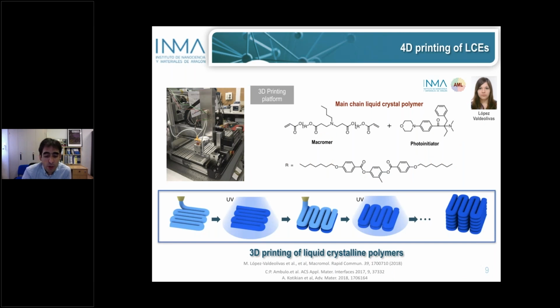In this scenario, we have developed a printing platform of liquid crystal elastomers. We did this at the same time and independently from two groups in the US, the group of Professor Taylor Ware in Texas and Jennifer Lewis and Timothy White in Harvard, that essentially demonstrated simultaneously a similar principle. In our lab, we have prepared this main chain polymer that you see in the top part of the slide, with reactive acrylate groups, together with a photoinitiator, a molecule that allows the polymerization of the system. We have printed these chains, and after the printing, we have fixed the material with UV light. The UV light excites the photoinitiator, and it polymerizes these acrylate-containing molecules.